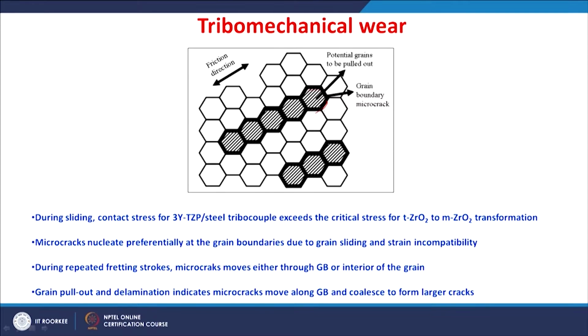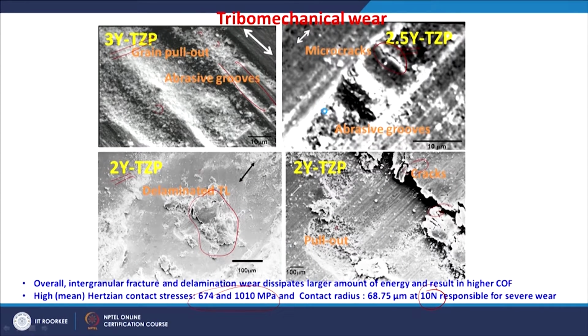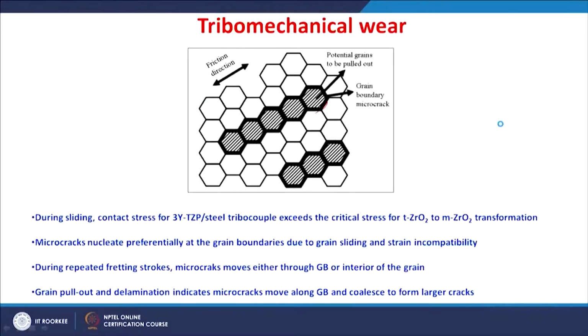So, our worn surface analysis indicates there is a large amount of pullout. Pullout generally happens when the grain boundary is a weaker region and the crack propagates through the grain boundary, and the whole material of the grain is removed as a pullout. So, it indicates the crack propagates through the weaker region, which is the grain boundary. It is schematically shown here: because of the repeated fretting strokes, these microcracks propagate preferentially through the grain boundary. So, the grain pullout happens and of course, the delamination of the layer.